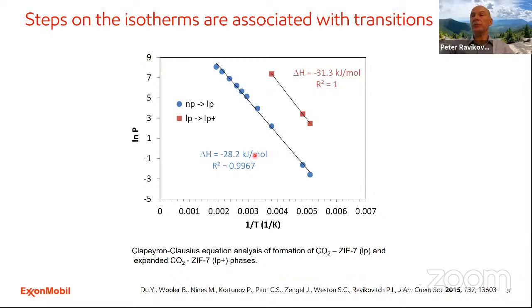You can calculate the enthalpy of the process associated with this transition. You can also plot pressures corresponding to the second step, and you can see this is a different transition. And you can calculate the enthalpy of this transition. So this type of analysis is very useful when you have isotherms with steps.